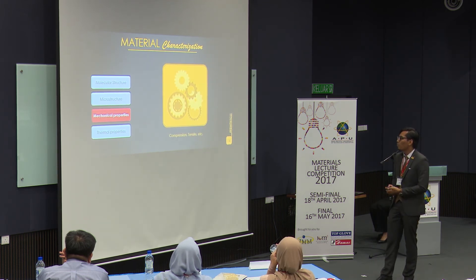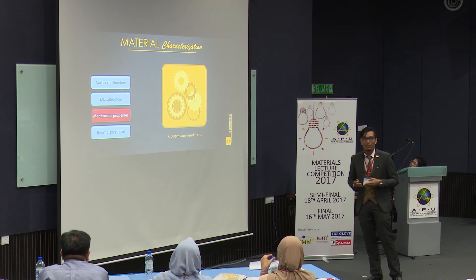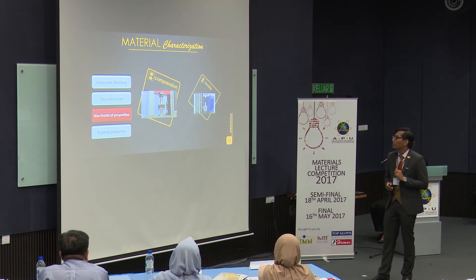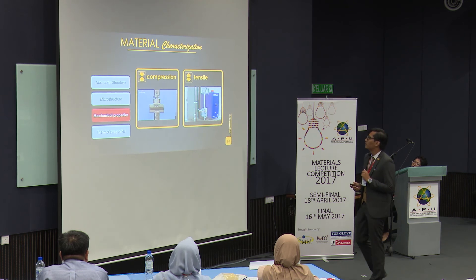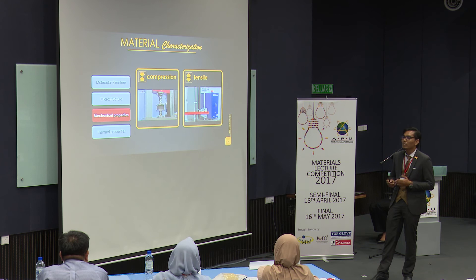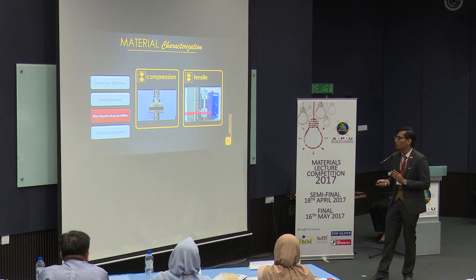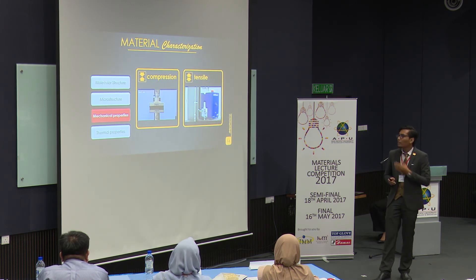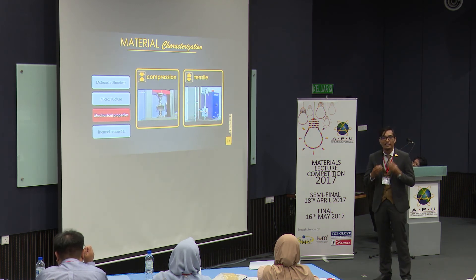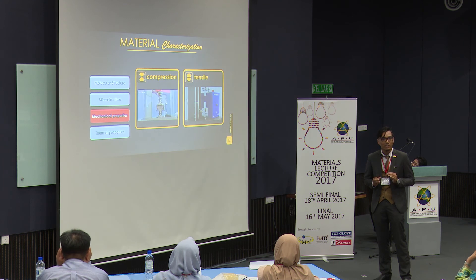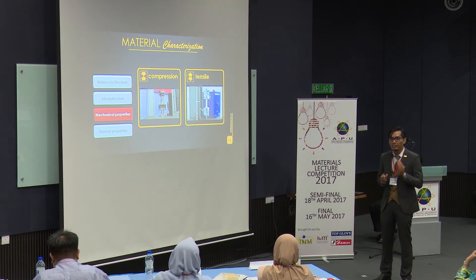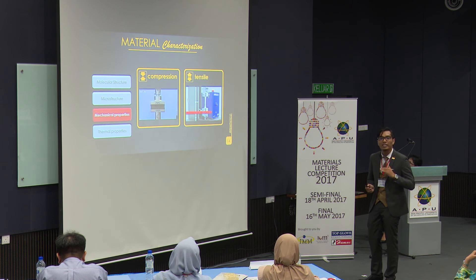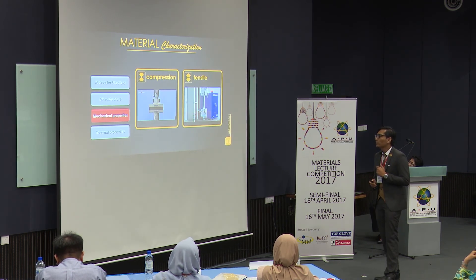Mechanical properties can be obtained by performing specific mechanical tests on the sample — for example, compression and tensile tests. Compression is simply pressing the foam together until it starts to deform, and tensile is pulling it apart until it fractures. The purpose is to obtain the mechanical data, because certain industrial applications require specific levels of mechanical strength. For instance, to be used in industry, the compression strength of any polymeric foam needs to be at least 180 kilopascals.